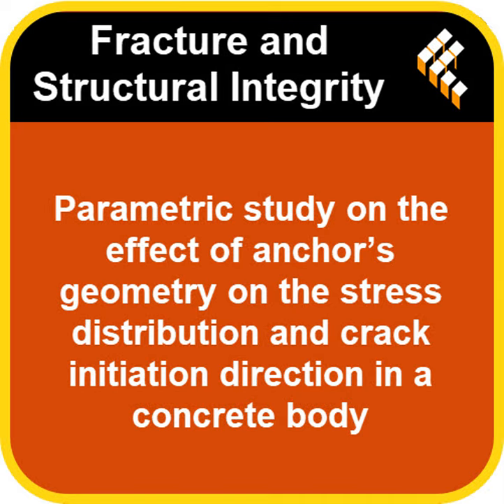And that direction gives them the predicted angle for the cone failure. Precisely. And the really cool part, the angle where their model predicted the highest tangential stress matched up really well with the angle people actually observe in real lab experiments, around 37.5 degrees. Oh, wow. Okay, that's strong validation then. The model seems to capture something real. It does. It suggests the model, even with its simplifications, is getting the fundamental crack initiation direction right.